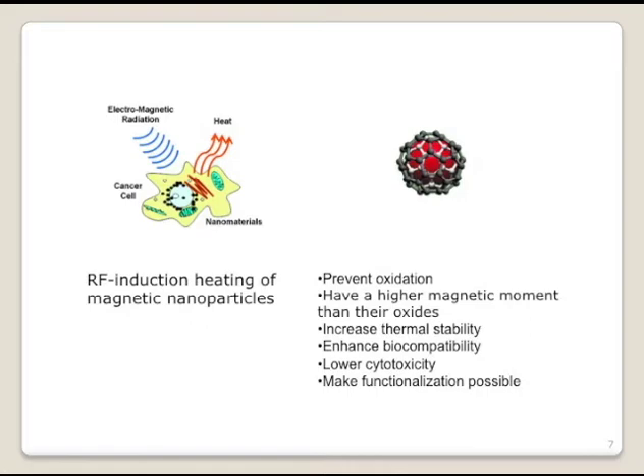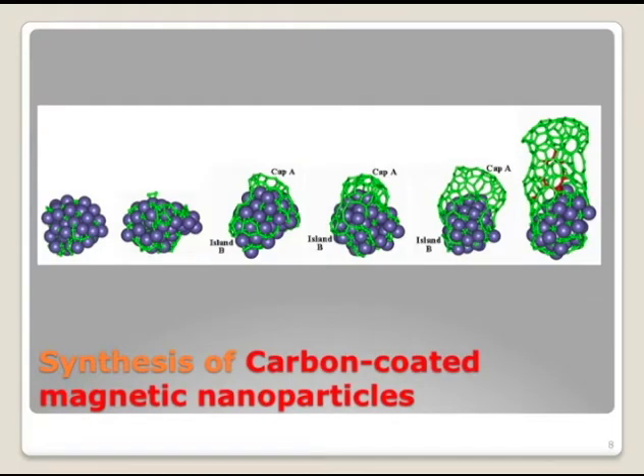How to make this kind of coated magnetic particles? From carbon nanotube synthesis, we got some hint. This is a schematic diagram of how a carbon nanotube grows from metal particles. Usually, these metal particles are iron, cobalt, or nickel, transition metals. We know that carbon-containing molecules decompose on the surface. They arrange themselves, then form a carbon-covered layer. When more carbon atoms are added into this system, the system becomes unstable. That grows the carbon nanotubes.